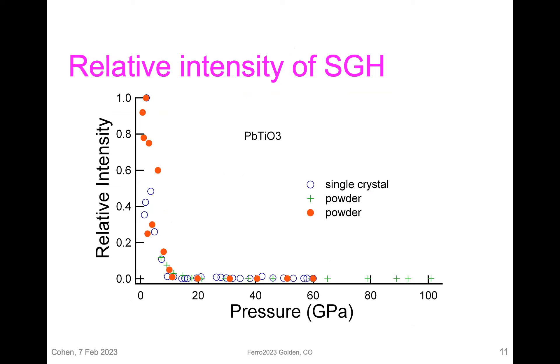These summarize many experiments, both single crystal and powder, at room temperature and 10 Kelvin. What happens is the second harmonic generation signal goes to zero at about 10 GPa — completely consistent with the 1980 Raman experiments — and then just remains measurably zero up to 100 GPa. So not consistent with the DFT calculations. We tried everything with the experiments and there was just no way to measure any signal.